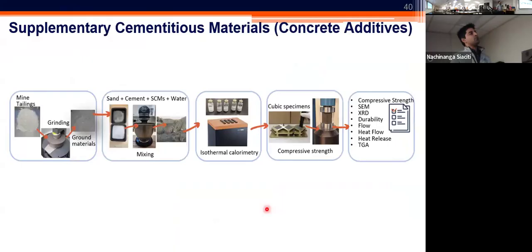In addition, we are working on developing some supplementary cementitious materials from mine tailings, again, because of the presence of the aluminosilicates. Sometimes all you need to do is to finely grind your tailings and incorporate them in the structure of the concrete with the hope that you would have tailing-based concrete additives that would then facilitate better formation of the cement hydration products and improvement in the durability of your concrete. So that's another track that we are working on.